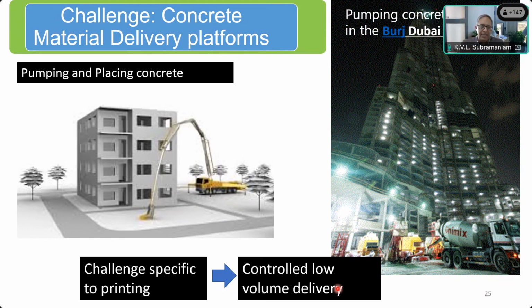Here, with the current technology, we are limited to about 4 to 6 millimeter sized aggregate. What is the consequence of that? The consequence is that my concrete mix that I use for printing tends to be paste rich. So I use more cement than I have to. So that's a negative that we have with this technology.